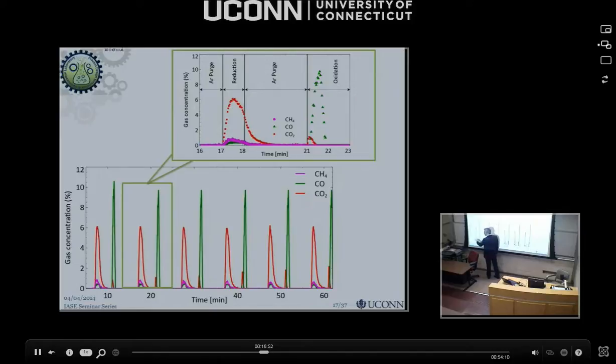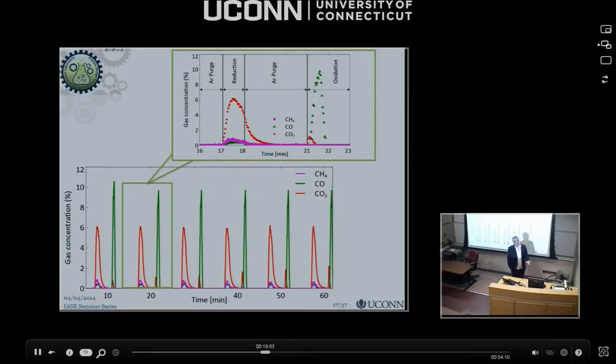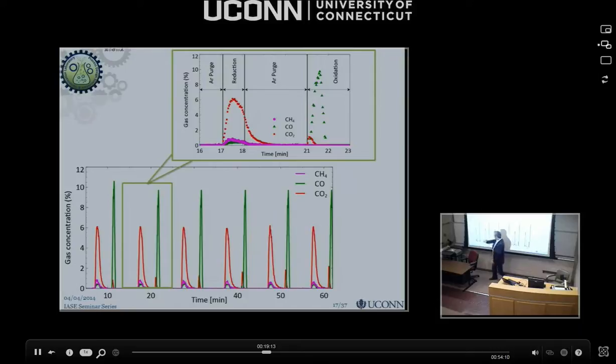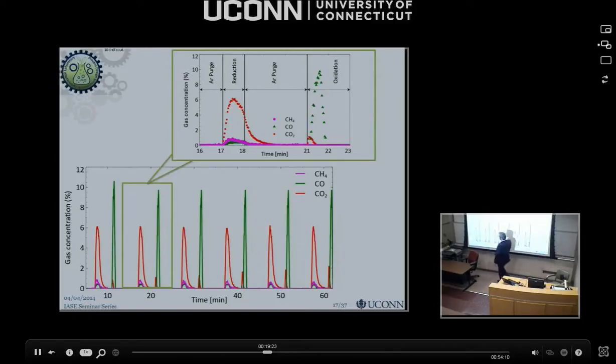We over-reduce the nickel oxide to nickel and then have carbon formation reactions. These carbon reactions, when you flow air through, burn the carbon and produce CO, and with a large excess of air, it's mostly CO2. That's a bad thing — it shouldn't happen in a commercial process. We run it like that intentionally because we want to study these reactions. Ideally, you would stop every time at the peak of CO2, and you wouldn't have any carbon formation.